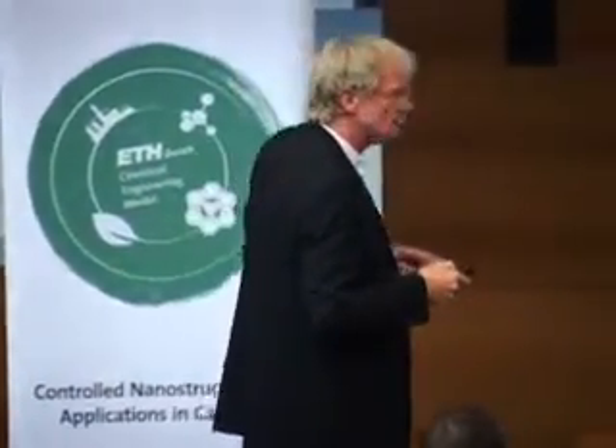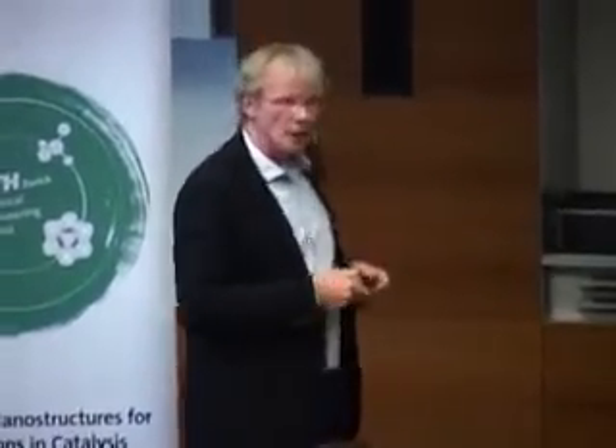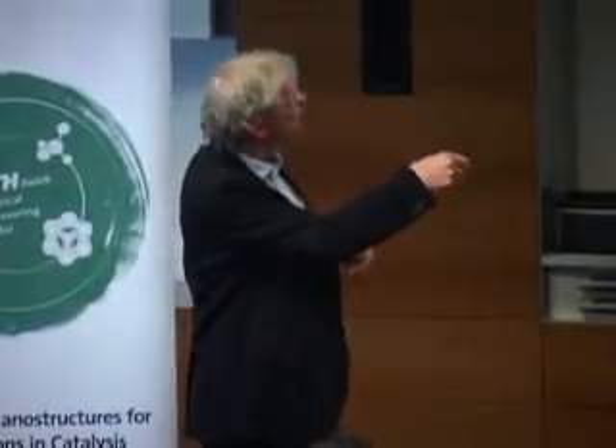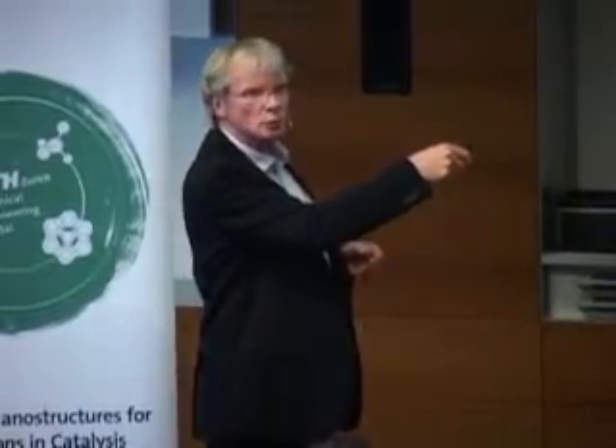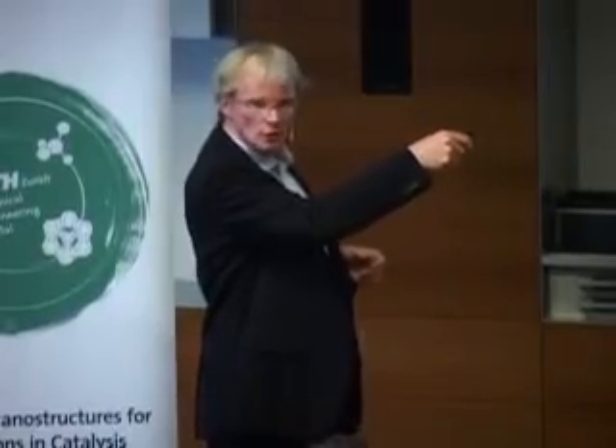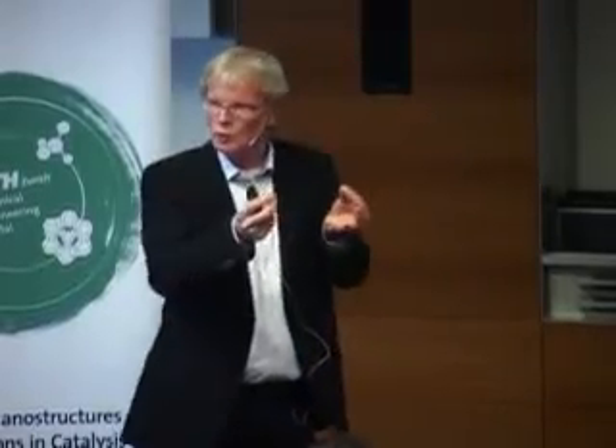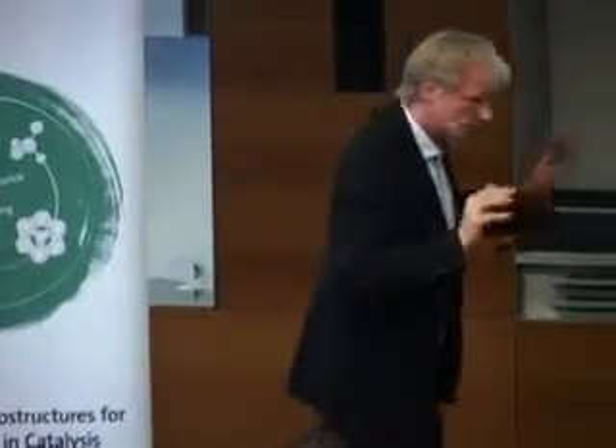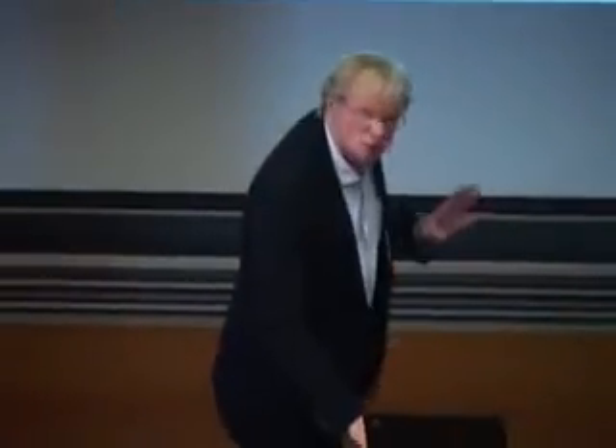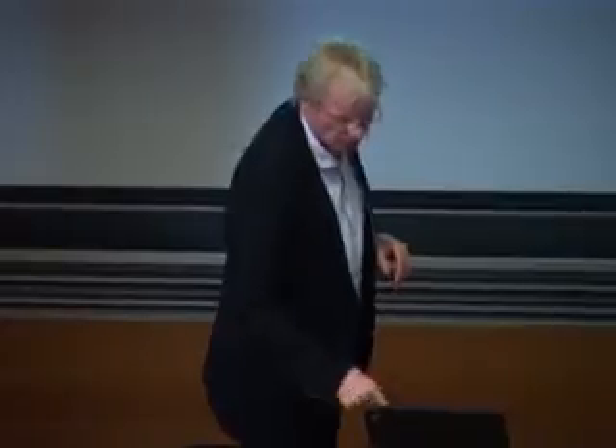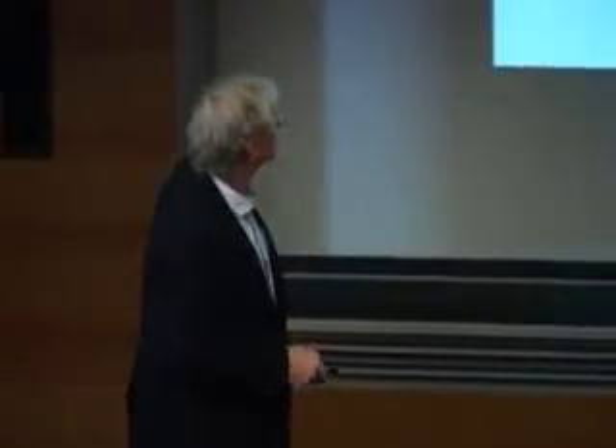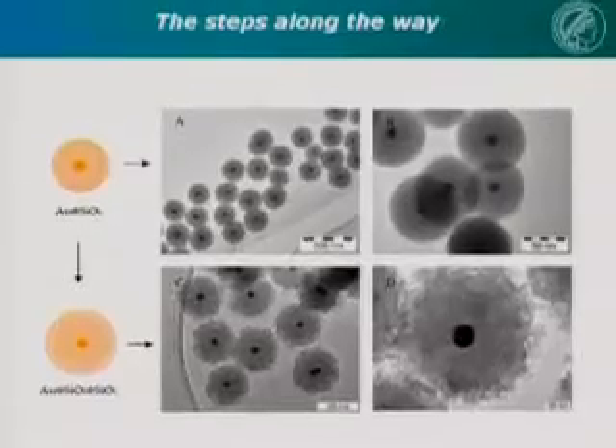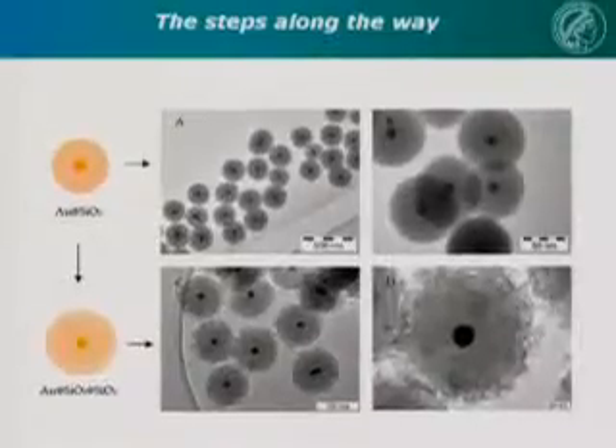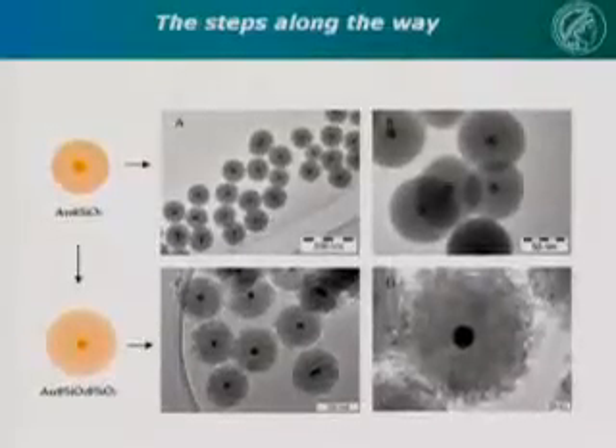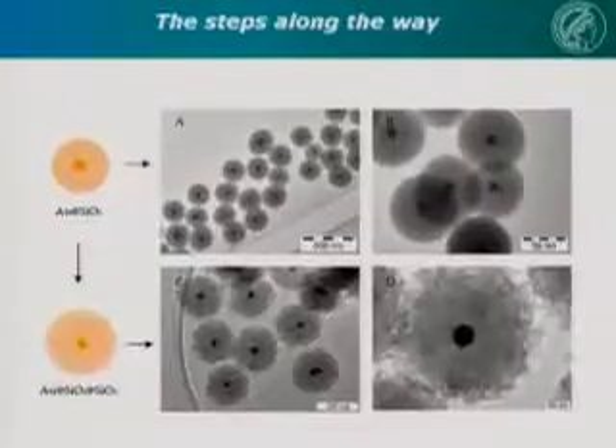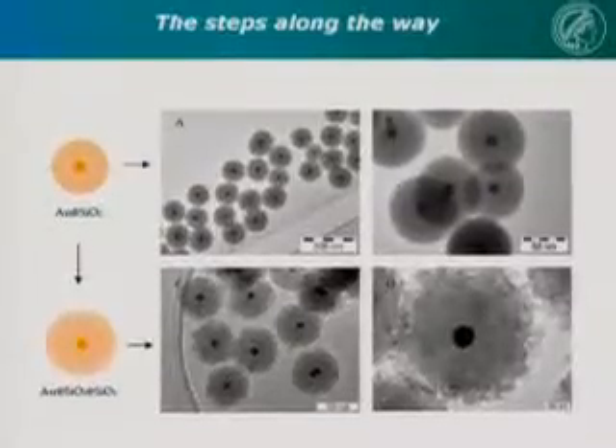It actually turned out later that the better way to do it is not to produce zirconia on a silica shell, but to produce porous silica on a solid silica shell and then fill the pores in the porous silica. But that's a detail about which you don't need to worry. It's just that the quality of the materials gets better. So just so that you see we can do it. This is now the silica-based route, so gold in solid silica, in porous silica. So here is the gold in solid silica. Here it's coated with porous silica.